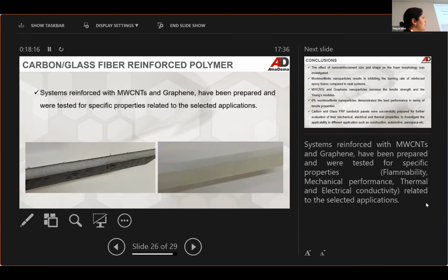And what we have observed is that systems reinforced with multi-wall CNTs and graphene have very good affinity with the face sheets. I'm not sure if you can tell, but basically we have managed to incorporate these as cores with the face sheets that you see here in black. These are carbon, and with the glass fiber face sheets that you can see here in white. And this is opening the way to our next experiments, which will be to check the effect, let's say, on the performance of fiber reinforced polymers when epoxy foams are used as cores.